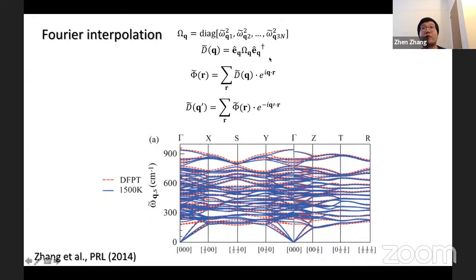Then by Fourier interpolation, anharmonic phonon dispersion was obtained and compared with that obtained by perturbation theory. Here I show the anharmonic phonon dispersion at 1500 Kelvin. It can be seen that in the Brillouin zone, the irregular frequency shifts generally exist, including red shifts, blue shifts, and unchanged phonon frequencies.